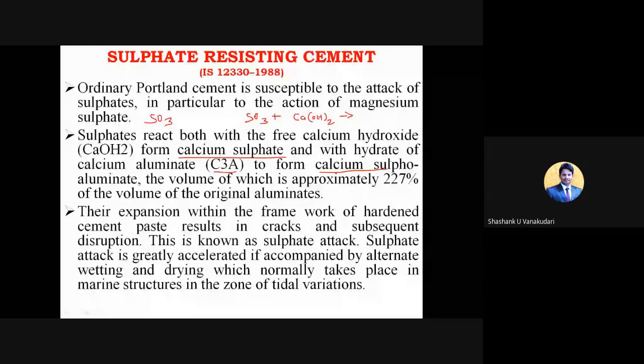So whenever this calcium sulfoaluminate compound exceeds in the cement, it results in the hardened cement paste developing cracks and subsequent disruption in the structural element, and this is known as the sulfate attack. Sulfate attack is greatly accelerated if accompanied by the alternate wetting and drying process. Alternate wetting and drying means, you can see in the summer season in the morning it will be too hot, and suddenly the rain comes, and again the next morning it will be too hot. So it's like the alternate drying and wetting process. Because of this, the calcium hydroxide present in the cement reacts with the water, and again the sulfates present in the cement content form the sulfate attack here.